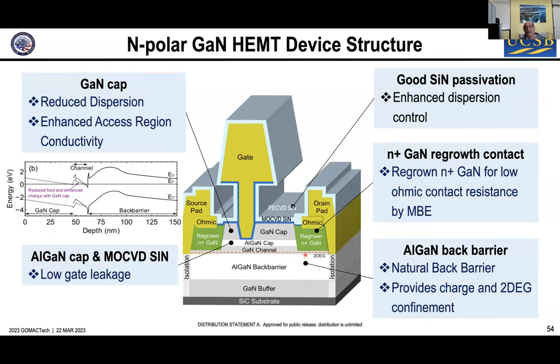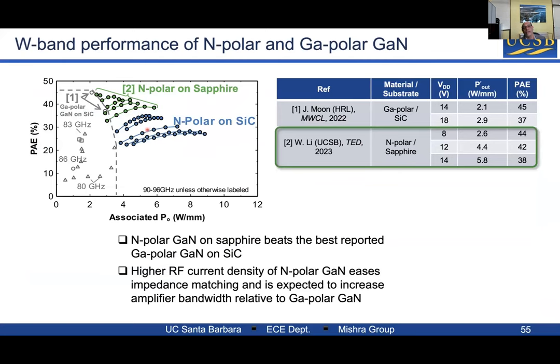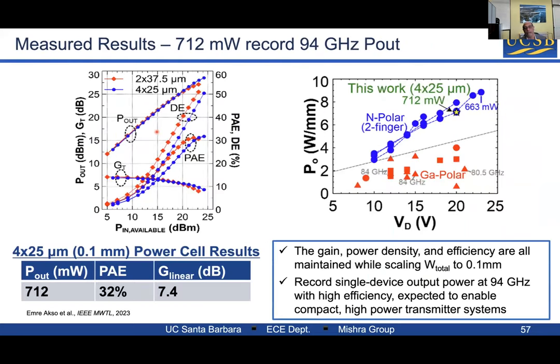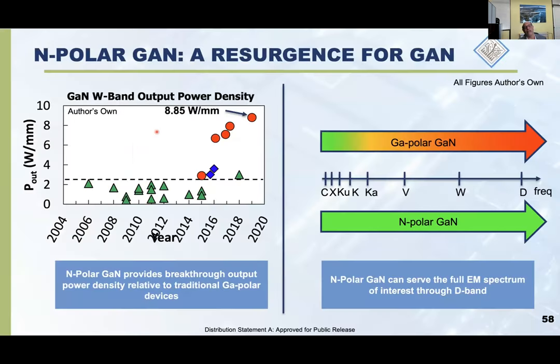These devices tend to have extremely high efficiency. So you can see here that the efficiency is extremely high compared to gallium polar GaN. Gallium polar GaN cannot even provide power above 4 watts per millimeter. So above 4 watts per millimeter, only nitrogen polar survives at very high efficiency. So, in conclusion, gallium nitride is actually going to serve the full space from low frequency to very high frequency. Some of it will be gallium polar, some of it will be nitrogen polar, but it'll be all GaN.